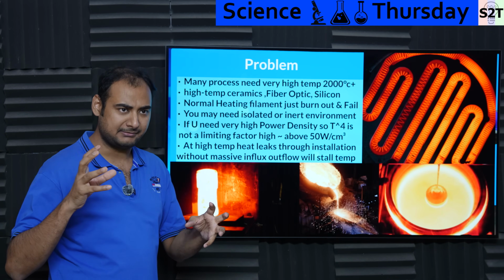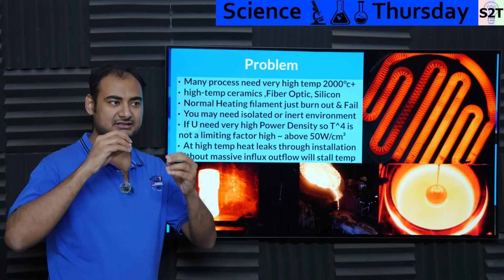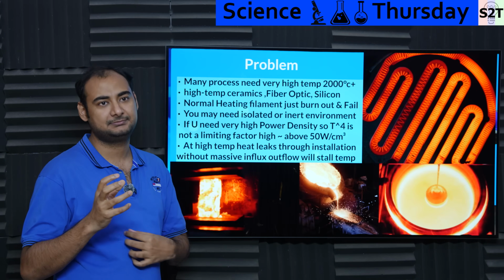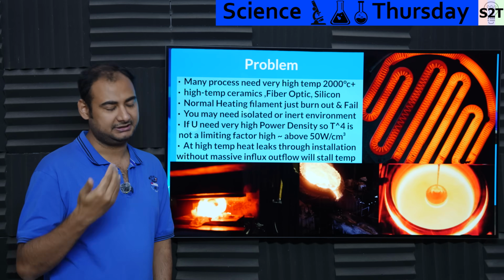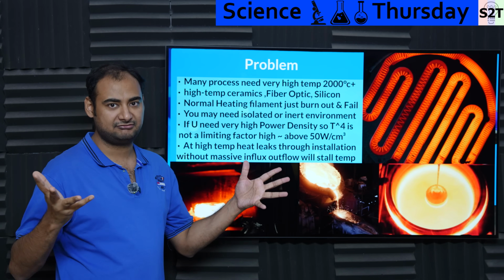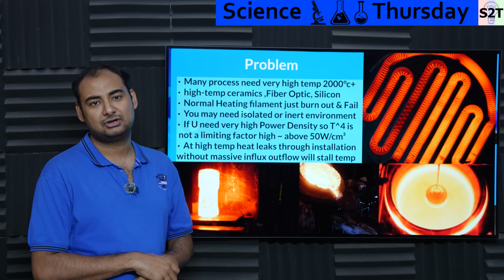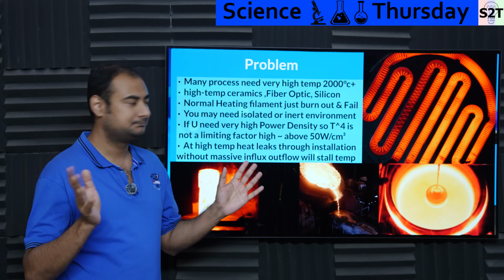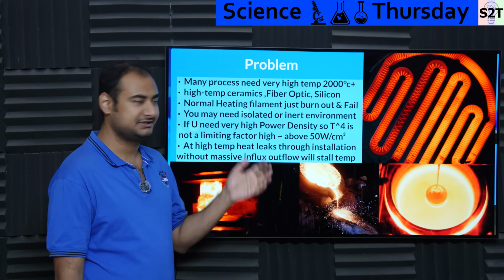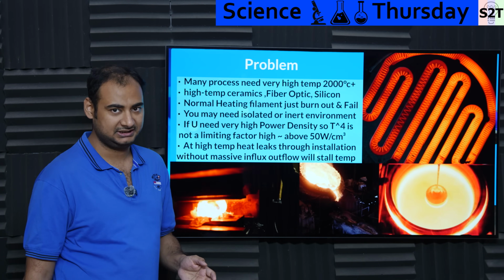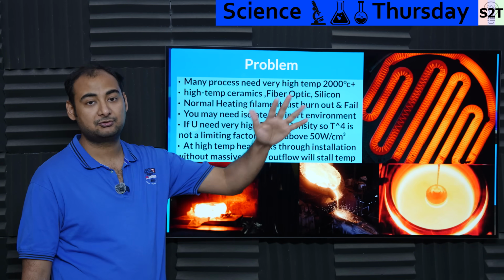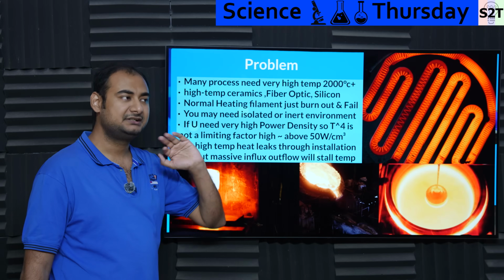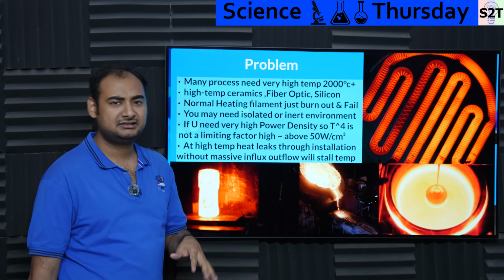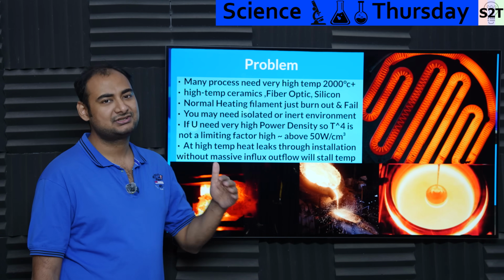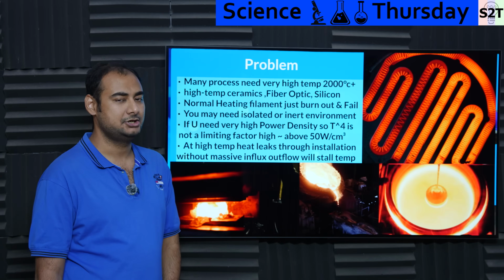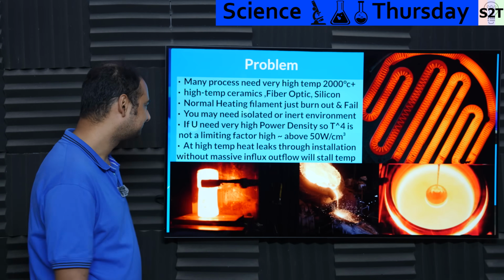Even with infrared lamps, where the energy is coming from the filament, if the filament heats up too much, it will get damaged, boil off. Basically, electrons will physically boil off. All of those will cause a fundamental issue where it's like, nope, it's not going to last long enough. Basically, it's going to burn out and fail very quickly. Specifically, if you go above 1000 sustained, meaning till 1000 you can push it. 1100, not too bad. The moment you start to touch 1200, 1300, it's like, nope, no sir.